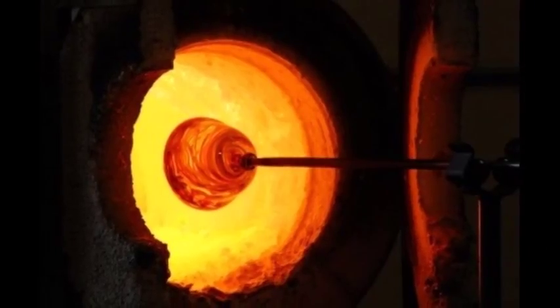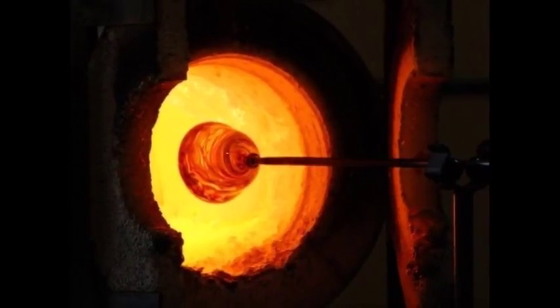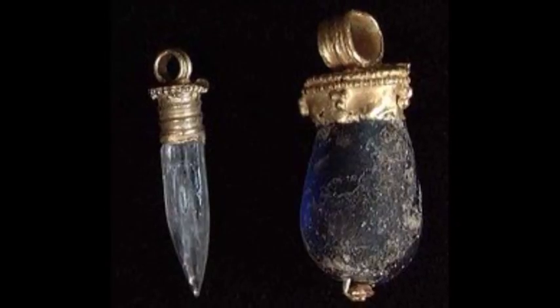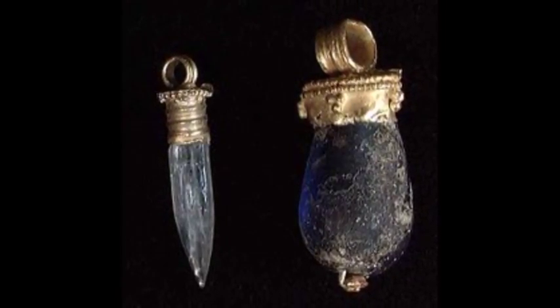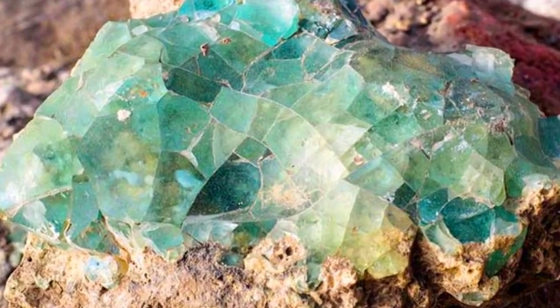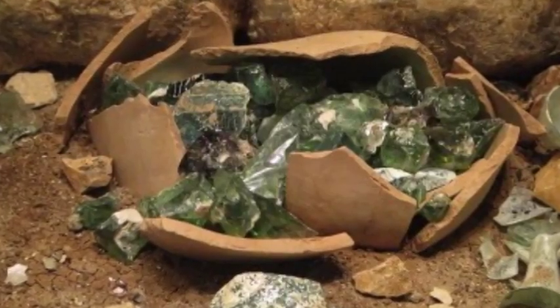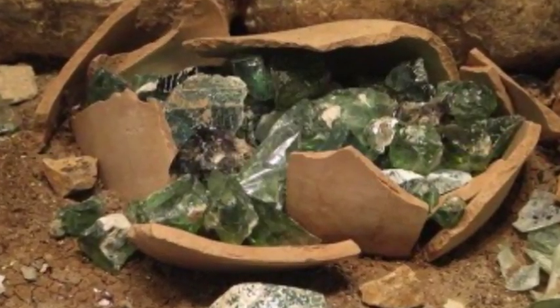Glass making in ancient times was often carried out in 2 stages. The first was an engineering stage, the hot, hard, dirty work of heating the granular raw materials to a temperature of about 1100 degrees Celsius, around 2000 degrees Fahrenheit, in order to bring about the chemical reactions that transformed them into a fluid melt. When the melt cooled down from this near-white heat, it set up into a glass. Having this work out of the way, the raw, unshaped chunks of glass could be transported to smaller factories where artisans would reheat the glass to soften it and fashion it into wares. The second stage could have been carried out 20 feet away or 500 miles away.